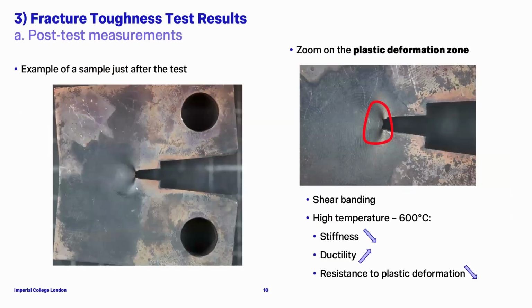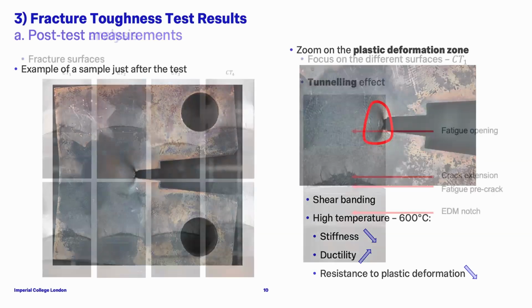Here's an example of a sample I just obtained after the test. It is quite obvious there's a huge plastic deformation zone here with a huge contraction effect and kind of shear banding. It is worth remembering that at high temperature, the stiffness of a material decreases while the ductility increases, and overall the resistance to plastic deformation decreases. So this huge zone might have an impact on my results, but I'll show you later on.